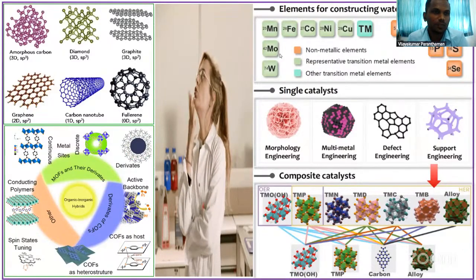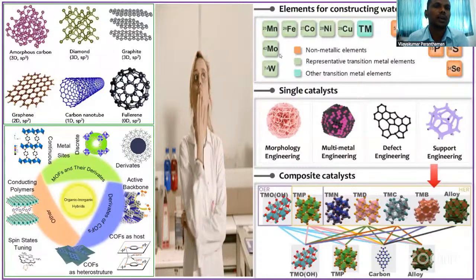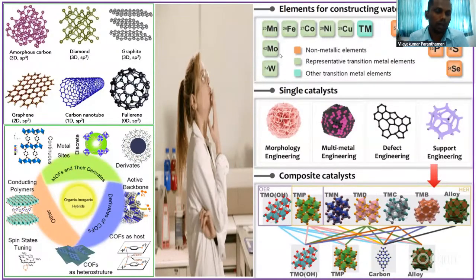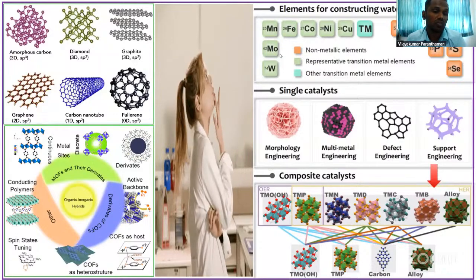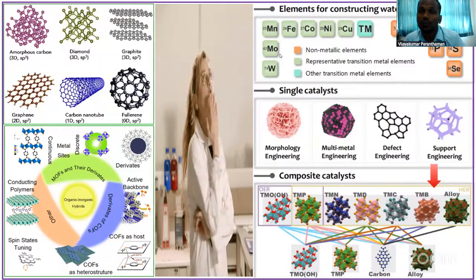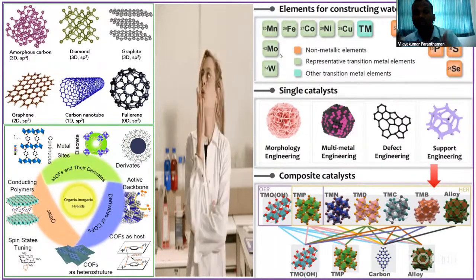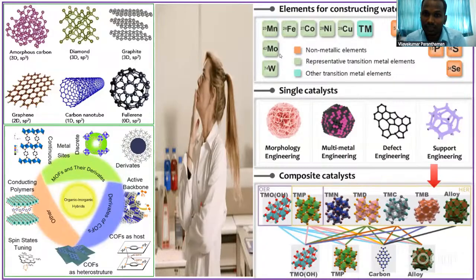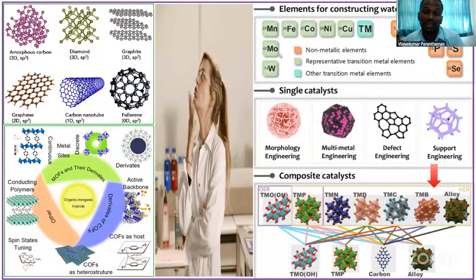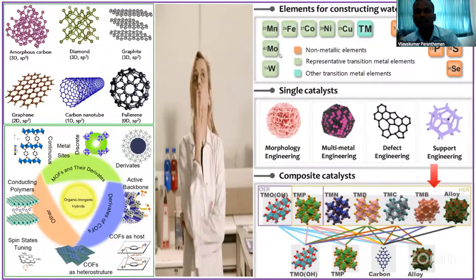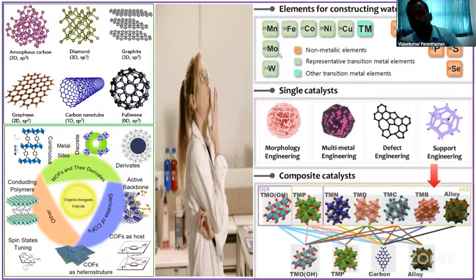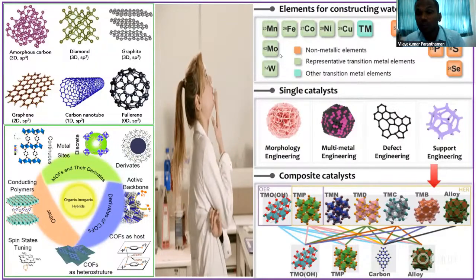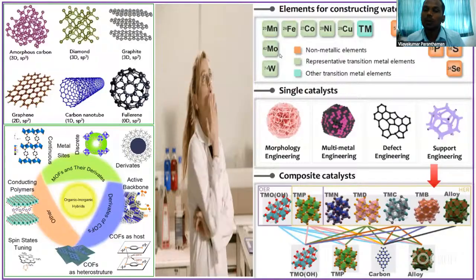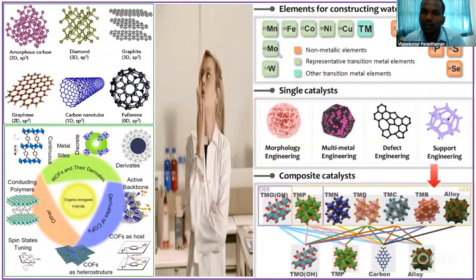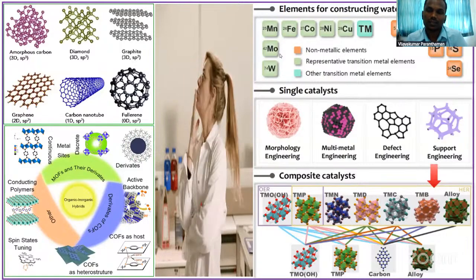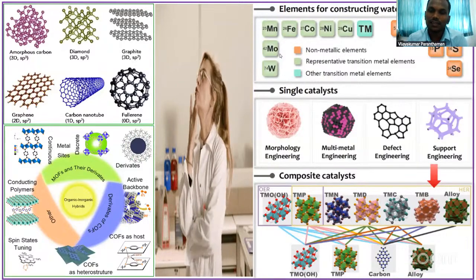These are some materials that have been developed, like carbon allotropes: amorphous carbon, diamond, graphite, graphene. Also some metal organic frameworks, MOFs and COFs, as well as some platinum-like behavior of transition metal derivatives, early transition metals, some metal-free catalysts, as well as some alloys, and transition metal derivatives like transition metal phosphide, nitride and dichalcogenides, transition metal carbides. Based upon the alloys, different combinations have been tried, but the success rate is still lagging.